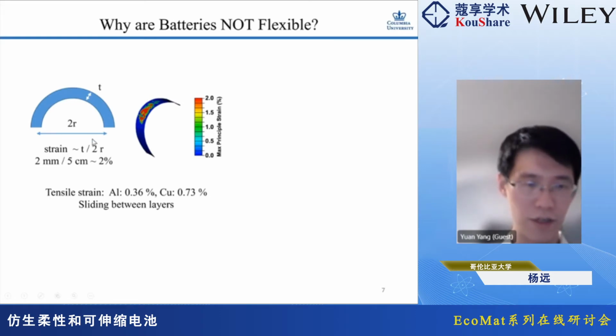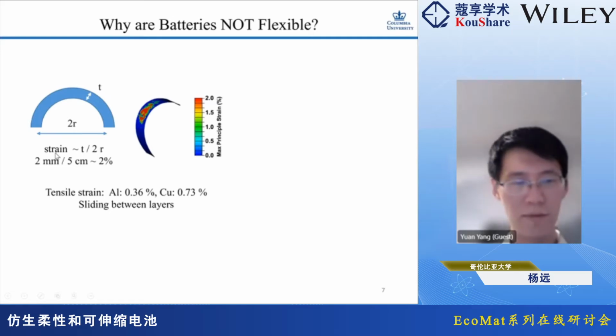the strain inside is proportional to the thickness over twice the radius, or the diameter. So for a battery with a thickness of about 2 millimeters, similar to the thickness of batteries in cell phones, even if we just bend it to a diameter of 5 centimeters, the strain inside is up to 2%. This is also confirmed by simulation. You can see that the strain can reach about 2%. Such strain is much higher than the tensile strain in metal foils, such as aluminum and copper. Tensile strain means the reversible range of strain, so that the materials are not damaged.